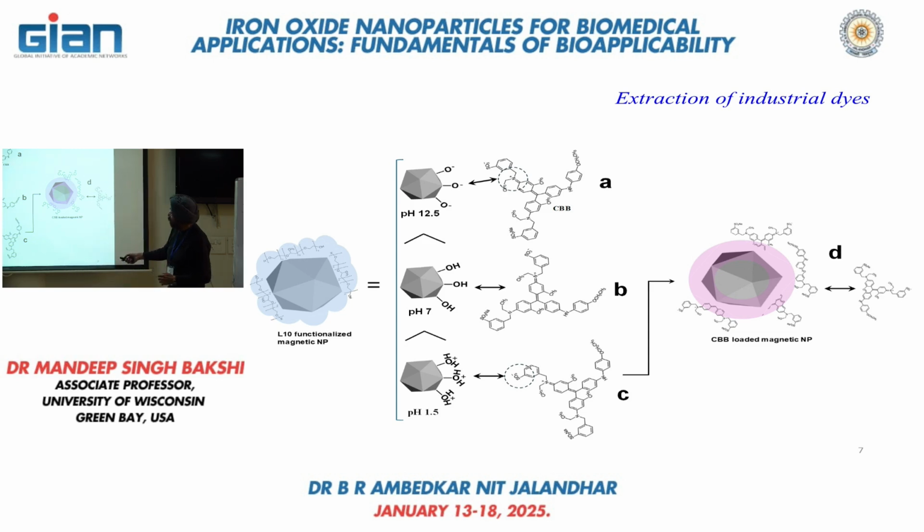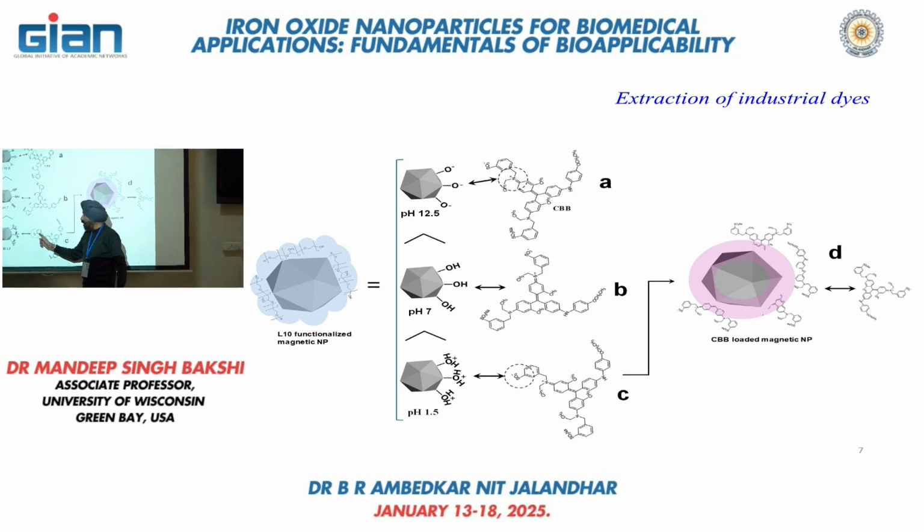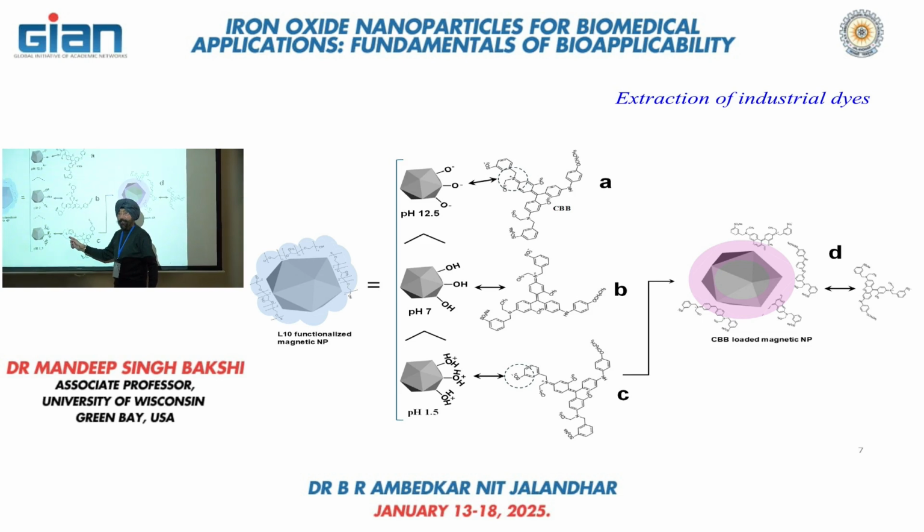On the contrary, you see over here, when you have a protonated hydroxyl group in the acidic medium, this is not a problem. For the protonated hydroxyl groups, the electrostatic interactions can easily be performed with the terminal group like this sulfonate group, and hence the extraction is very rapid.